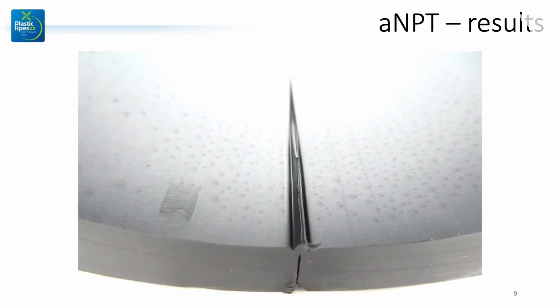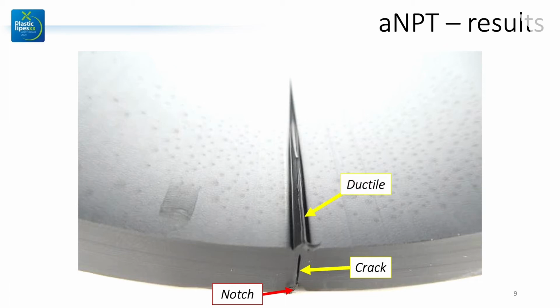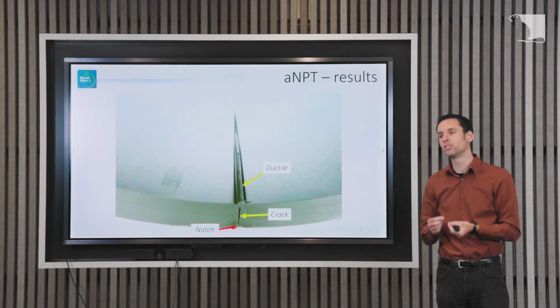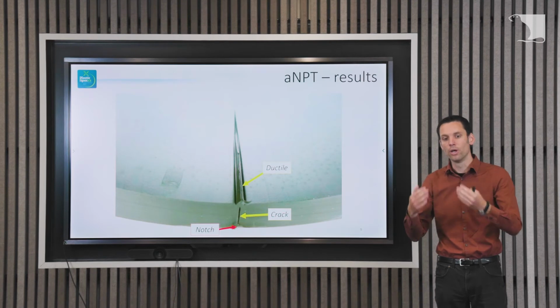Now the final crack that we can see here, because it completely went through: here we see the notch, we see a crack, and we see some ductile behavior on the inside. The crack is slow crack growth, so it's really brittle, but the end part, the ligament, is then so small that the pressure will deform it ductile. So we thought these are really interesting results because they gave us a very nice insight into the failure mechanism of the polyethylene pipe in the accelerated notch pipe test.